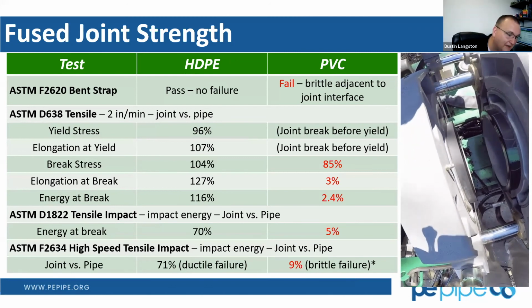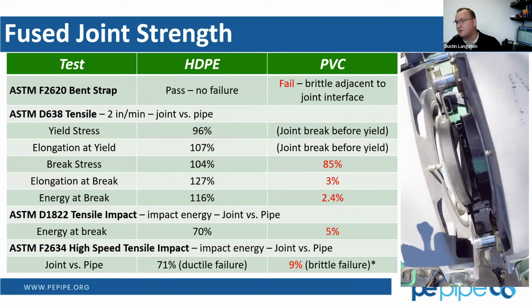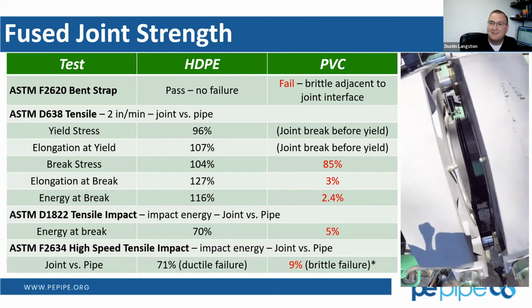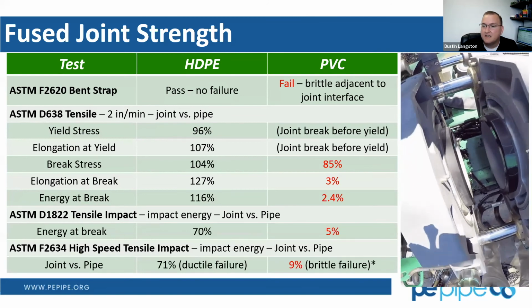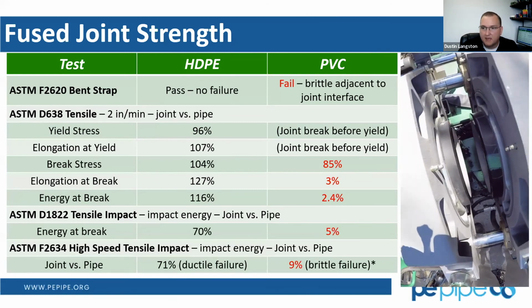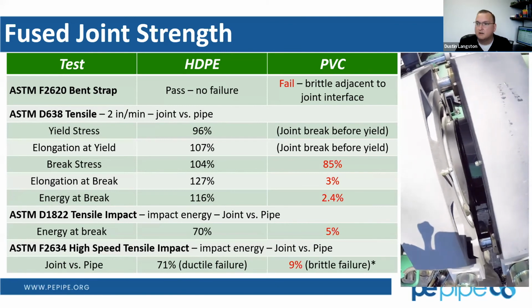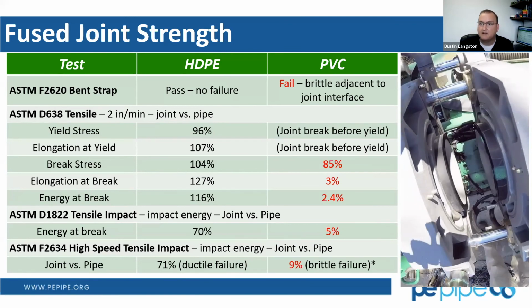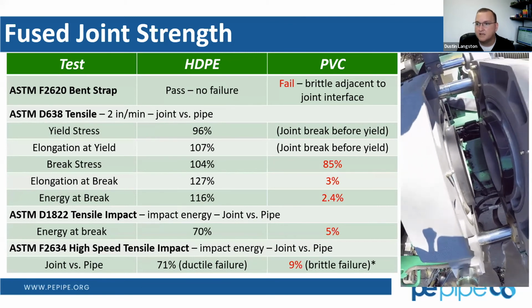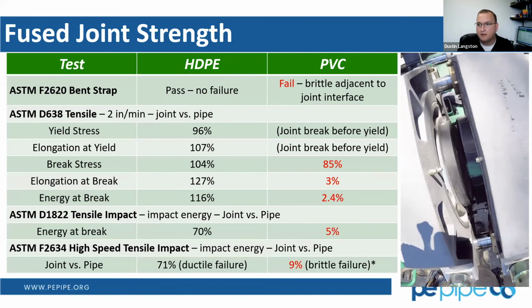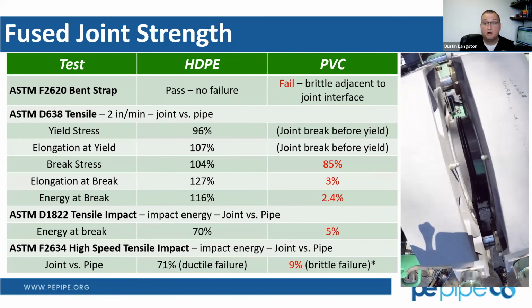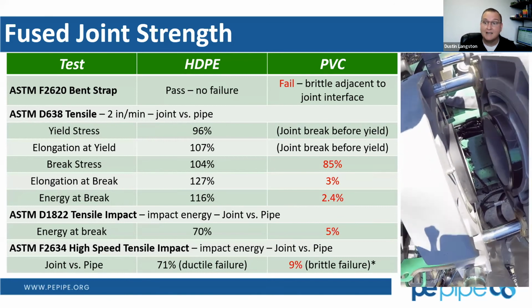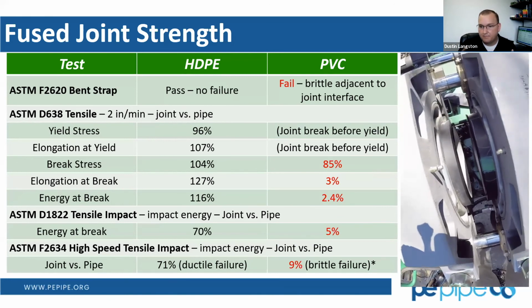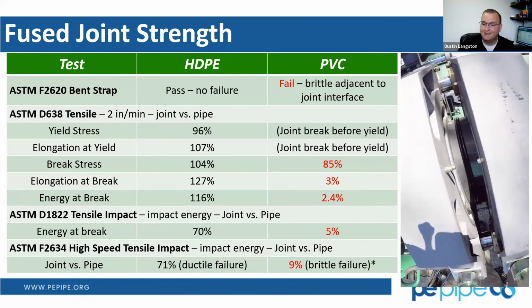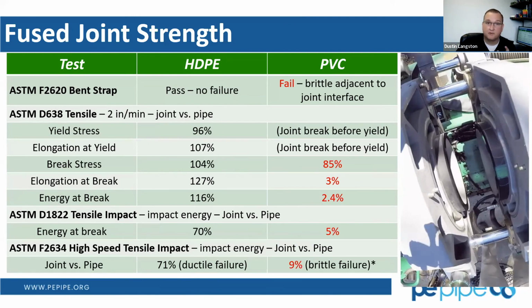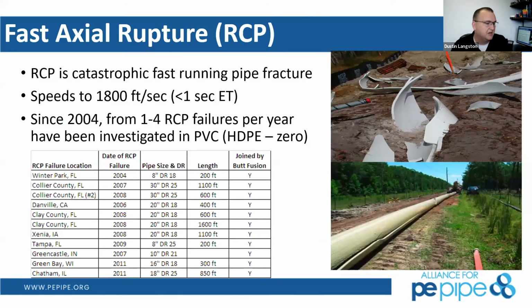And I'm sitting here trying to find on my desk my fused PVC sample. I have hundreds of these things to demonstrate what the difference looks like. But Stephen hit it right on the head. With a fusion for polyethylene, you have a full molecular entanglement that is providing not only the tensile strength, the same as the pipe, but also the ductility and bending of the pipe itself. And we'll really drive that point home in a few slides when we talk about swage lining and tight fit liners. But again, the tensile strength of a fusible PVC is not that of the pipe strength, versus a polyethylene, which is.